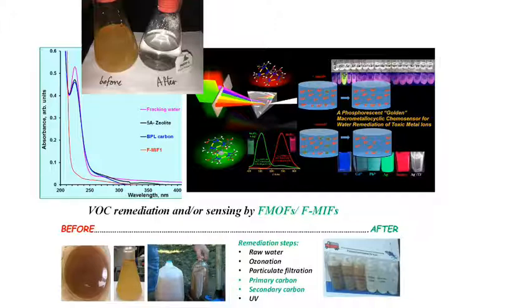All the crud is taken out, but it's still extremely contaminated, and we tried extraction. Naively, they said to my students, let's just do extraction to get rid of a lot of it and then purify the rest. And that didn't work. So we still had to deal with this sample here. If you look at the UV-vis spectra that show the hydrocarbon area, you see the hydrocarbon in the original fracking produced water here. We dilute it enough so we can measure it on the UV-vis.